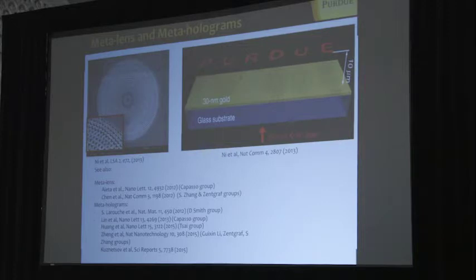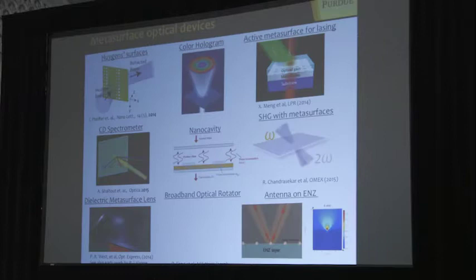And then you have this lens, which actually is a world record thin lens. In this case, it's a 30 nanometer thin lens. But you could do anything. And there is a lot of work done by many groups. By no means am I trying to pretend that we did the most important work, so I list some of them, just to illustrate. Of course, you could also make a hologram. By controlling the shift of phase at every single point, you could create any image you want at any distance. Because you control the phase, you actually have full control over light.